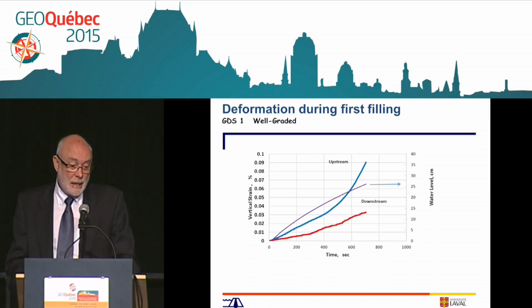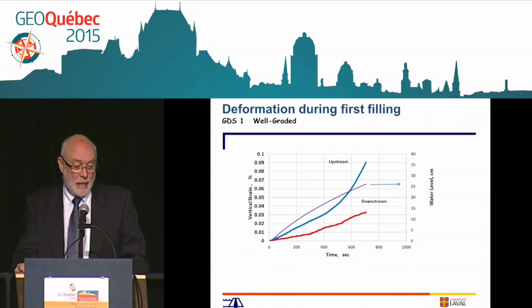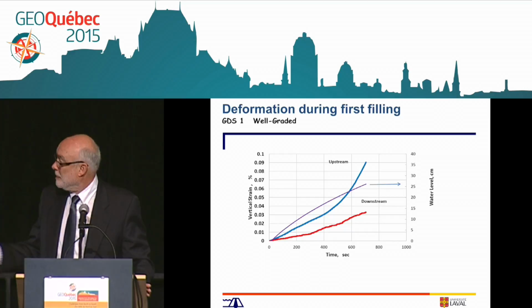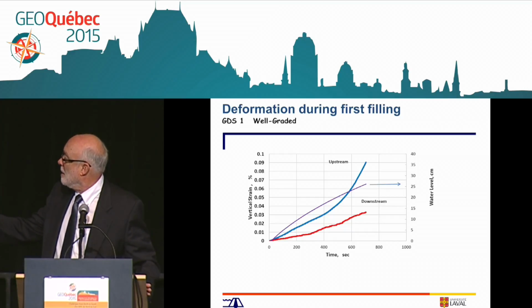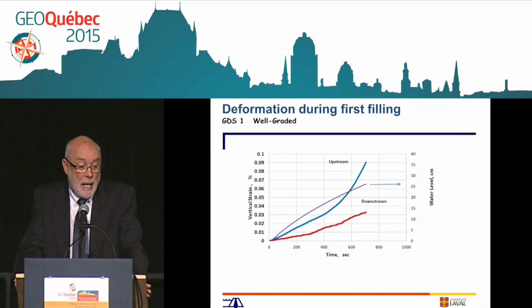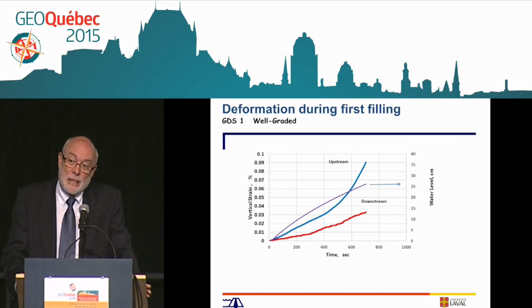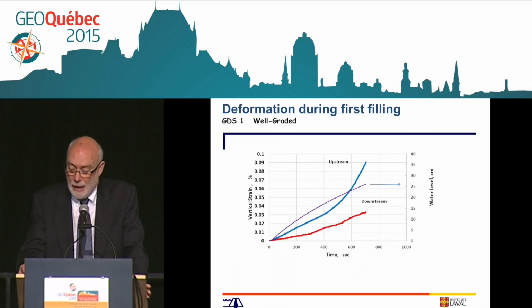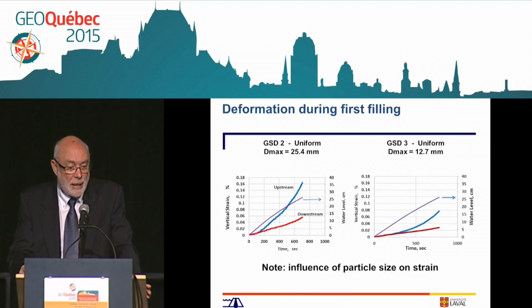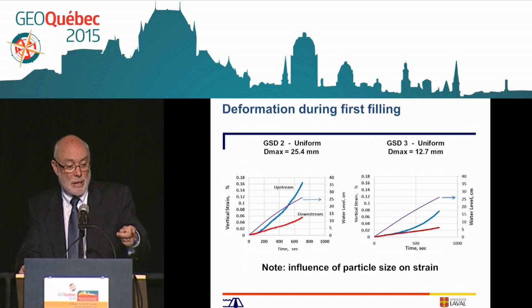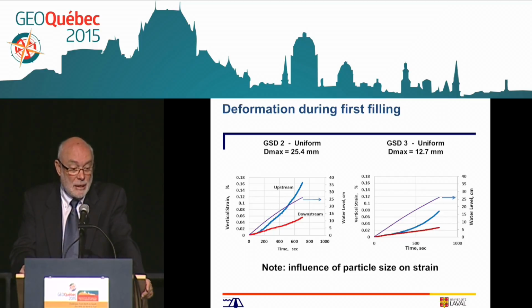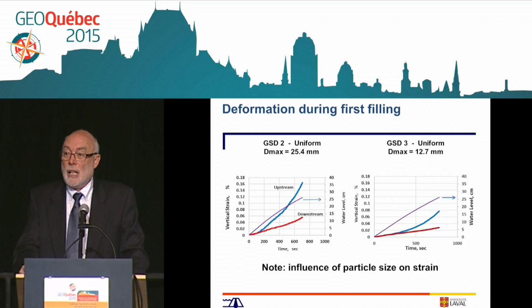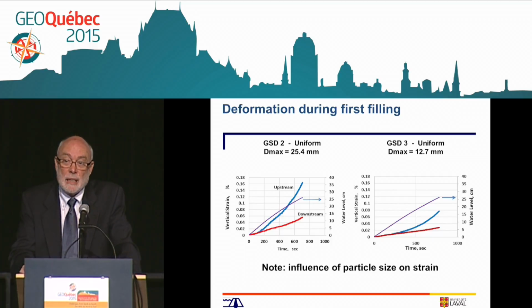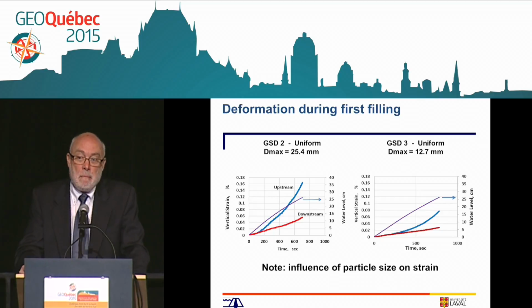This is interesting data. This is data that you probably have not seen often. The purple line is the reservoir level. That pointer does not seem to work. And the blue would be the settlement that is induced in the upstream, and the red in the downstream. So we see that the wetting does indeed create more settlement. And this compares the two uniform grain sizes. As you see, with the Dmax of 25 millimeters, the settlements are larger than when the grains are smaller, which again indicates that there is a scale effect in the behavior of rockfills.